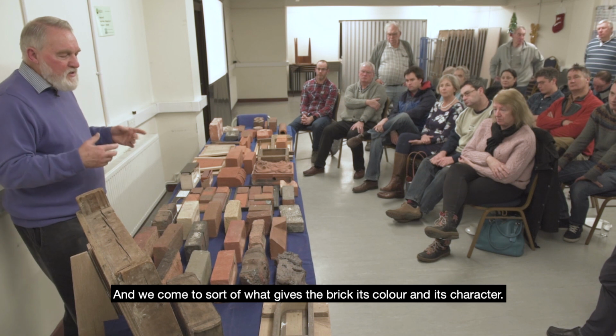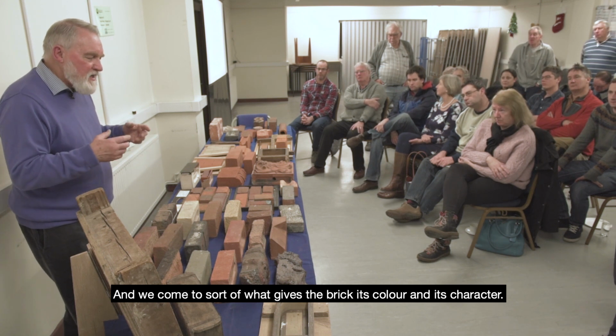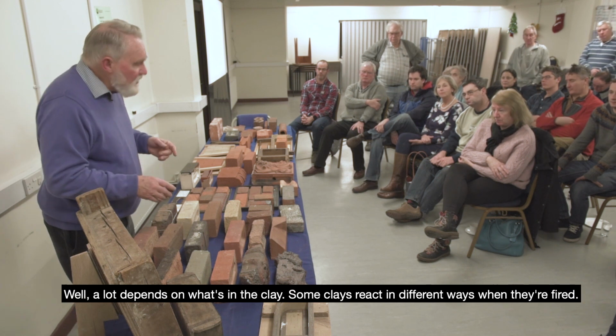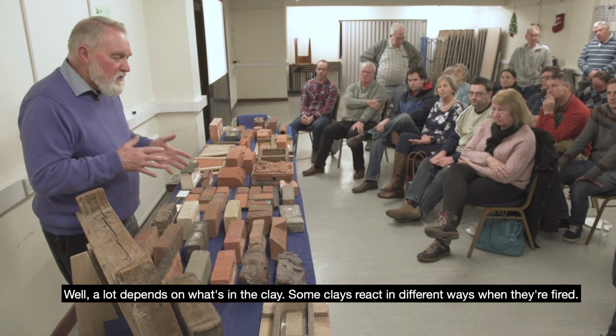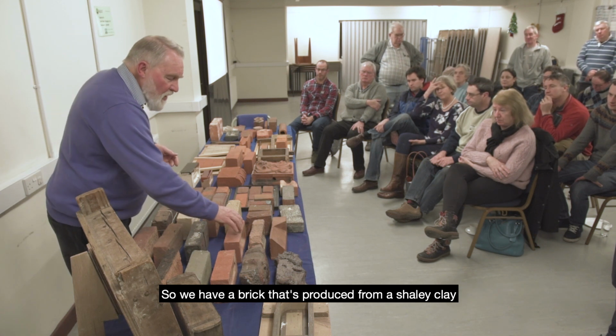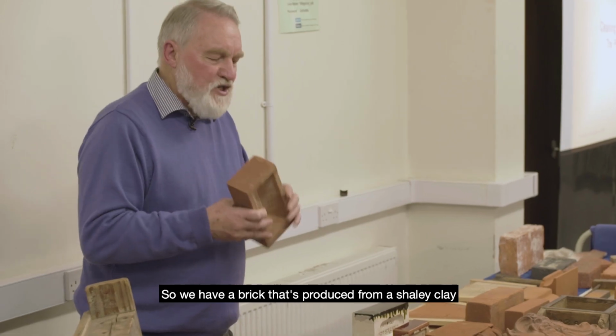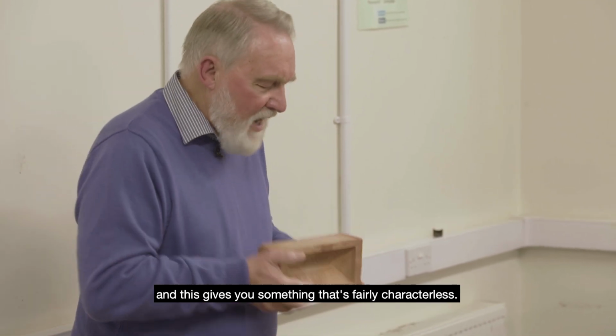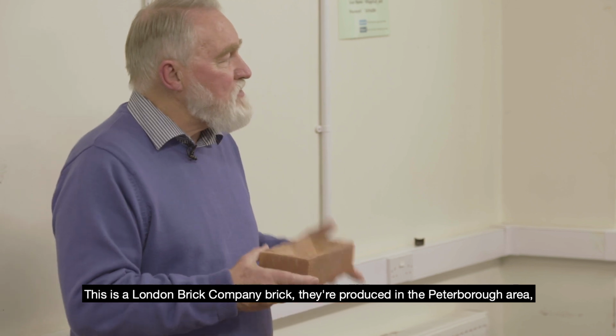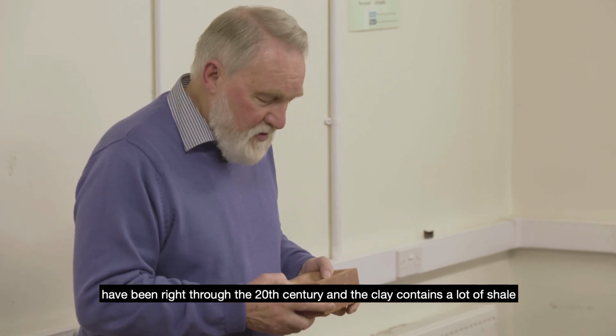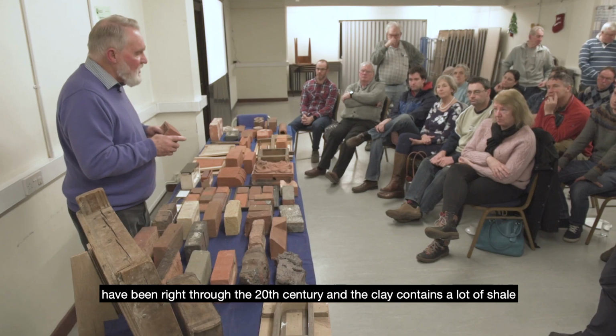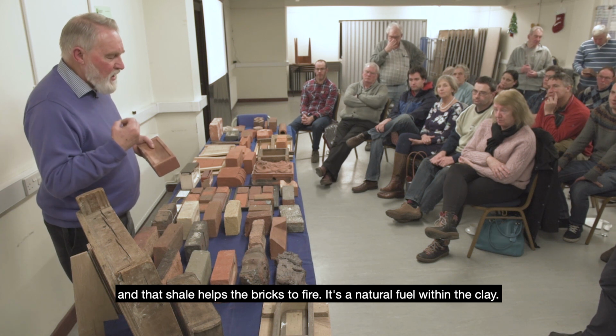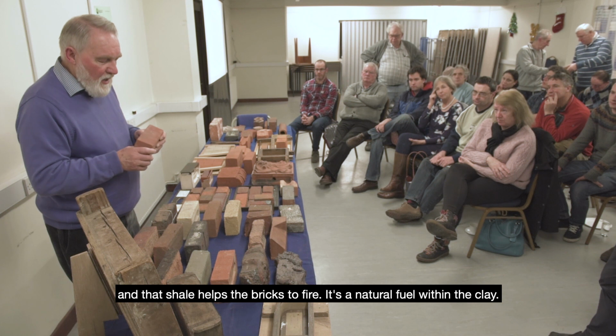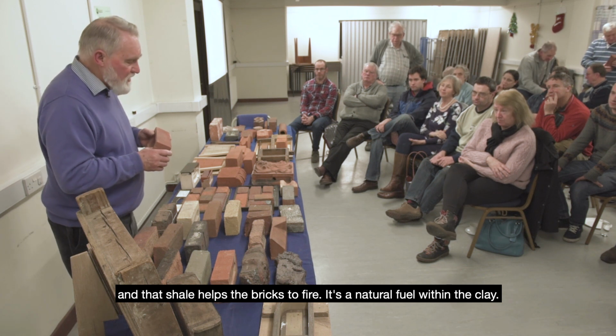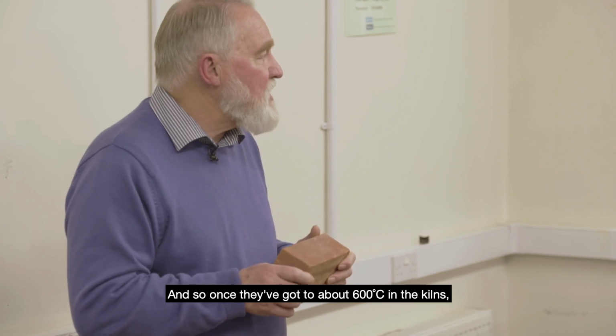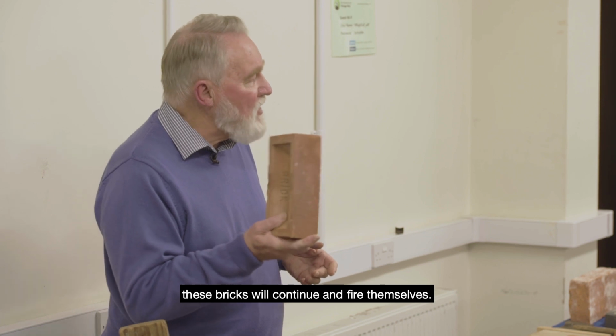And we come to what gives the brick its colour and its character. Well, a lot depends on what's in the clay. Some clays react in different ways when they're fired. So we have a brick that's produced from a shaly clay, and this gives you something that's fairly characterless. This is a London Brick Company brick. They're produced in the Peterborough area, have been for right through the 20th century, and the clay contains a lot of shale, and that shale helps the bricks to fire. It's a natural fuel within the clay, and so once they've got to about 600 degrees centigrade in the kilns, these bricks will continue and fire themselves.